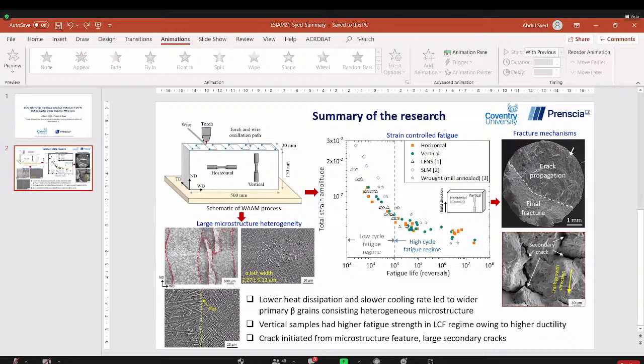Okay, I can ask a question. Well, the material was fabricated with wire arc additive manufacturing, and this technique, same as other AM techniques, would result in residual stresses in the component. I didn't quite find any info regarding the residual stress in the samples that were studied. Obviously, the mechanical properties that you're observing are not only related to the microstructure. There is a part that is the effect of the residual stress. What is your opinion? What do you think is the state of the residual stress in these horizontal and vertical samples, and in which case can it be more dramatic?